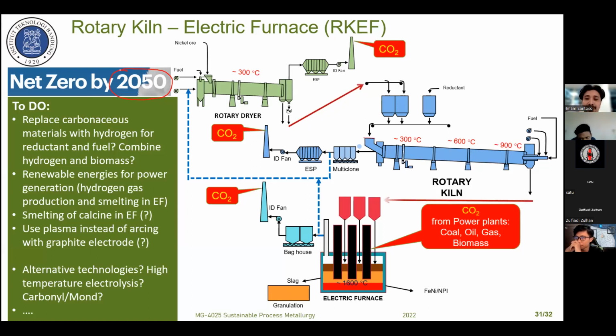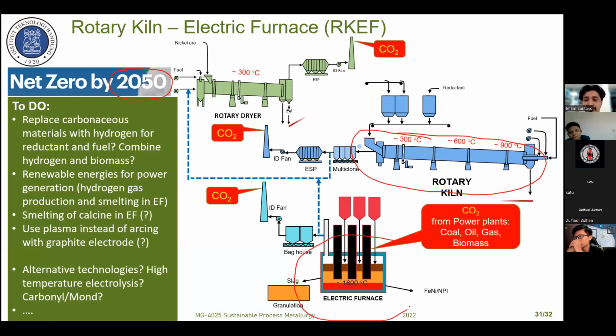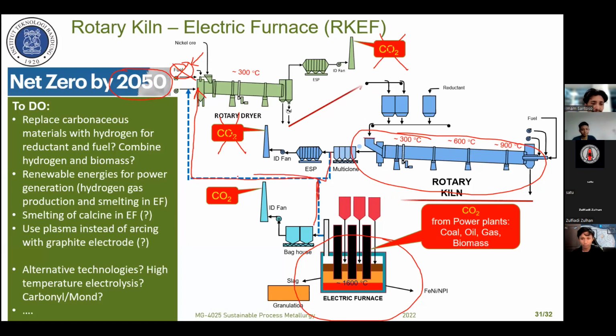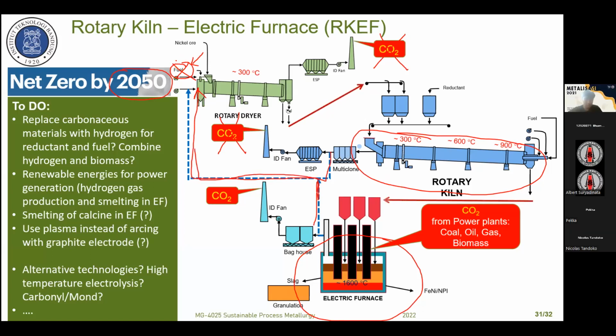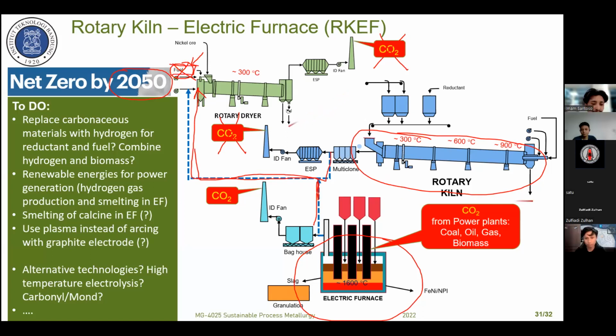Now, we also run experiments in our laboratory to simulate the rotary kiln and also the electric furnace by using pure hydrogen. We use hydrogen as a reductant, and the aim is to reduce the CO2 emission from the rotary dryer. Here, for example, if we use fuel, maybe gas, we should not use any fuel here. We can utilize the off gas from the rotary kiln and also from the electric furnace. In that case, maybe a small amount of fuel is required.